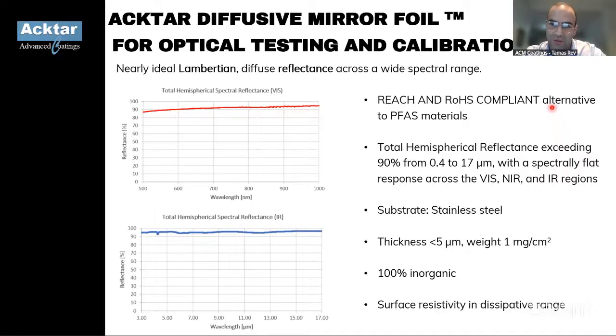alternative to PFAS materials. And as you can see on the optical graphs here, the total hemispherical reflectance exceeds about 90% in the visible range, so 0.4 to 17 microns. And this is provided with a spectrally flat response across these regions.